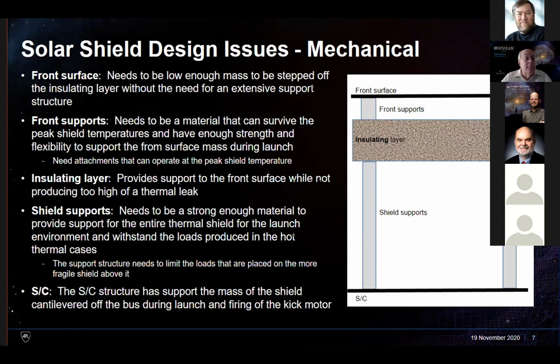expanding dramatically. And again, on Solar Probe at those temperatures, we were seeing an expansion of the shield on the order of a quarter of an inch, and the front surface would be even more. So you need to have flexibility in these materials and also strength. And again, you have to be able to bound these in ways that you have some understanding of what their limitations are, and then you need to be able to do the analysis that shows that the system will not only behave, but that there's positive margin for all cases. So you have to have material properties. You have to go through the regular analysis case, which can be seriously involved.